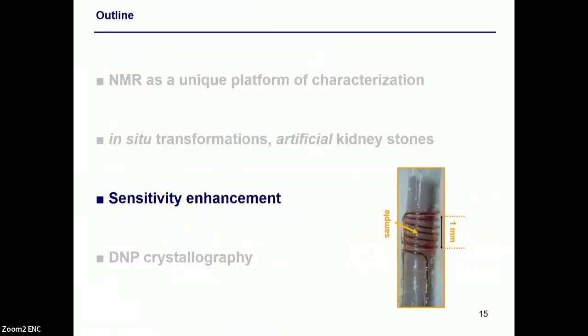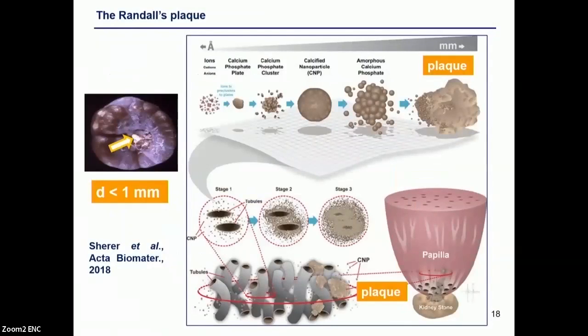As I told you, we are sometimes facing the problem of samples which are very important, but for which the mass is intrinsically low. So I introduce here a second part of the kidney stones, which is called the Randall's plaque. What is this Randall plaque? The Randall plaque is a sort of aggregation of hydroxyapatite. It's very small, and nobody knows exactly the structure of this. But what we know is that the plaque is developing here at the bottom of the papilla in the kidney, and it acts as a nucleus for the growth of a bigger calcium oxalate kidney stone. If you look carefully at this picture, you have here in the middle, in white, the Randall plaque. The dimensions are all sub-millimeter, meaning that the corresponding mass is, let's say, between 100 and 200 micrograms, okay?